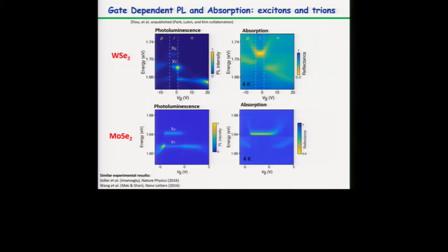Okay, this is some data that was taken in collaboration. All this work is taken in collaboration with the Park and Lukin group that I will acknowledge at the end. So this data was taken by Joe Shaw. He compared photoluminescence with absorption on tungsten diselenide and MoSe2. So I want to mention, as in the previous slide, we have this neutral exciton. We have the trion, which are these ones that move with carrier density. In either tungsten diselenide or MoSe2, we always have them, and they always go lower in energy with increase of carrier density.